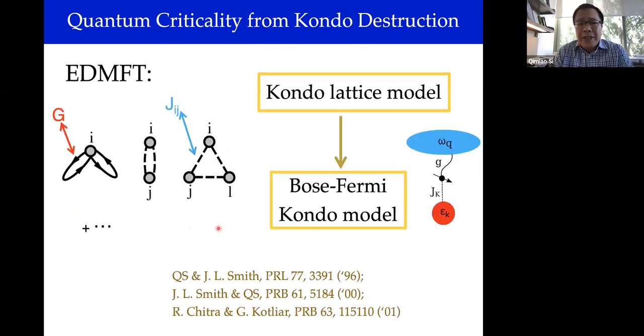And so I'll just very briefly mention the calculational scheme which we have employed. This is some extended version of dynamical mean field theory. I'm not going to go through the process, except to say it includes local correlations and the antiferromagnetic exchange interaction between the different sites. And in this approach, the local correlations are captured by the Kondo coupling of the local moment with a fermion bath, and the RKKY exchange intersite correlations are captured by the local moment coupled to a fluctuating magnetic field bath. And so that's the procedure that we're going to use.